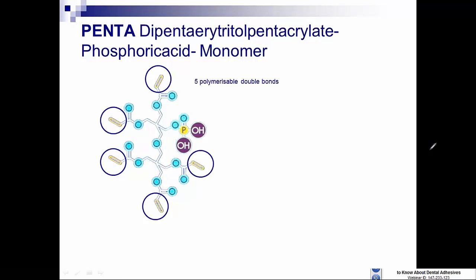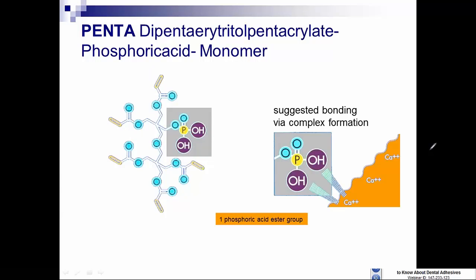This monomer is called PENTA, and there's a complicated chemical monomer on this. This acidic material does demineralize, but also bonds via a complex formation, a covalent bond with remaining calcium mineral apatite in the tooth. And this does add some stability and some sealing ability to the bond and the bonded interface using this acidic monomer.